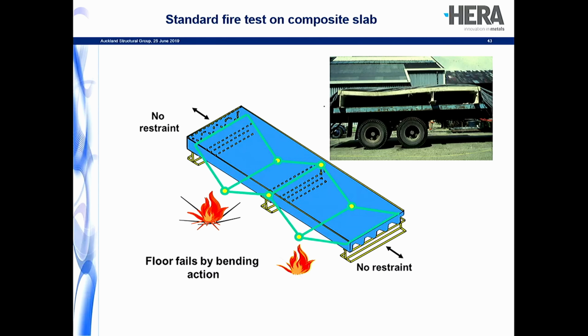So essentially, what's done in most manufacturers' design tables is that it normally assumes that you can get a plastic collapse mechanism forming in fire conditions. And top right basically shows what the slab looks like after a loaded fire test. So it's not such a severe deflection as you might think.